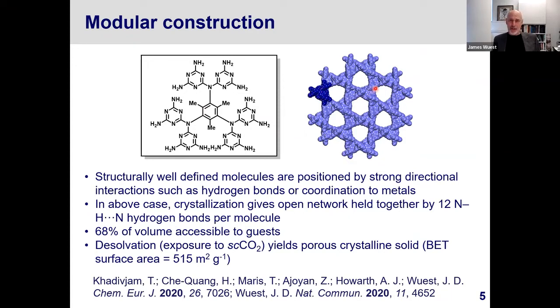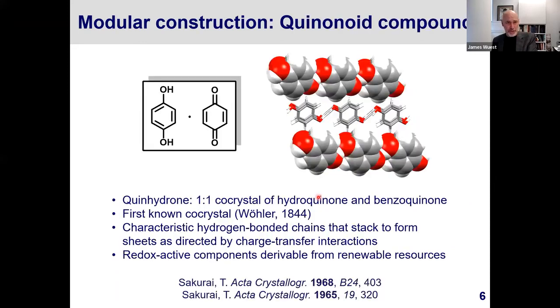About 68% of the volume of the structure is accessible to guests, and desolvation using the technique of supercritical CO2 yields a crystalline porous solid. The porosity in this particular case is relatively modest compared to other crystalline porous materials, but it's important to remember that this compound crystallizes in a way that's basically dictated by relatively weak NHN hydrogen bonds. This is work that was carried out in collaboration with a group of Ashley Howarth at Concordia University, and the reference is down here below.